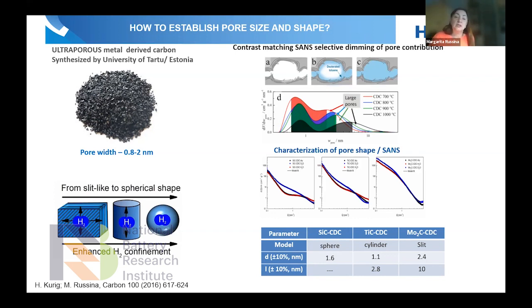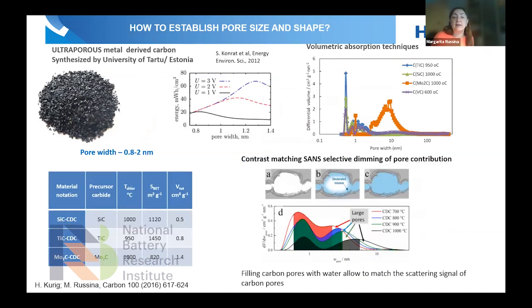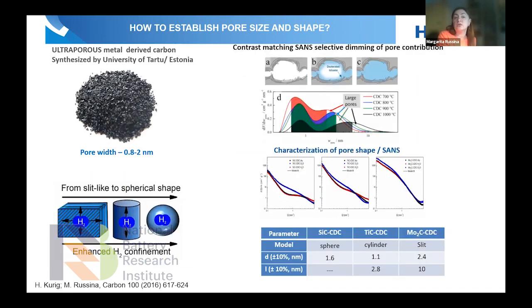And using this contrast matching technique, we could establish that the pores are not slit-like pores characterized by only one pore size, as was assumed in the past. What we deal with is a complex 3D pore size. In a simple system like this molybdenum mesoporous system, we have slit shapes. But in the ultra-porous systems like titanium carbide and silicon carbide, we have spherical and cylindrical pores. And they are characterized not by one size but by two: the width and the length. Exactly these numbers are reflected in these peaks here. So these are two characteristic numbers reflecting the pore size, and this information you can get only from the contrast matching technique, not from other methods.